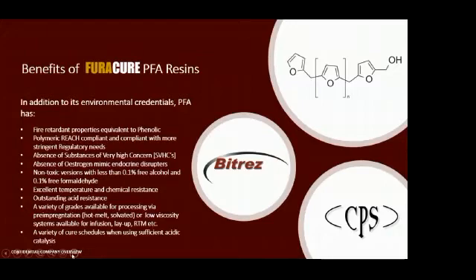And whilst, of course, we're targeting the two key areas of pre-preg manufacture, which is the hot melt and the solvated routes, we're also in the early stages of sampling and developing low viscosity systems for infusion and layup. It isn't without challenge. These materials are very pH sensitive, and the acid catalyst required to react them is a very delicate process indeed. But we see this as a fantastic opportunity for our business to improve our environmental footprint, and obviously support the UK composite sector with bio-based and more sustainable materials.